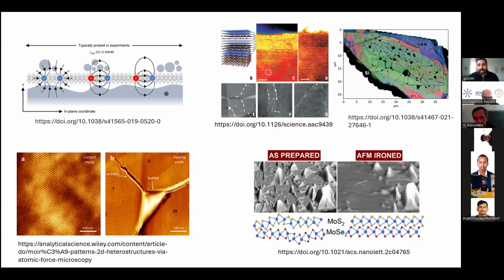Also, some pairs of 2D materials have this effect that is called self-cleansing. So they try to minimize energy by creating a uniform surface, and they will push away all the adsorbents that are on the surface. But these adsorbents might find some pinpoint positions like a grain boundary, a defect, a crack or something, and they will agglomerate there. As you can see here, all the black spots are air pockets that have contamination. And this translates to this thing here. Instead of having a uniform moiré periodicity and a system that will perform consistently the same way, you will have this, where the air bubble that you have here will disrupt the periodicity at this point, and it will also apply local strain that will change the periodicity from area to area. This is not something that you want in a device.